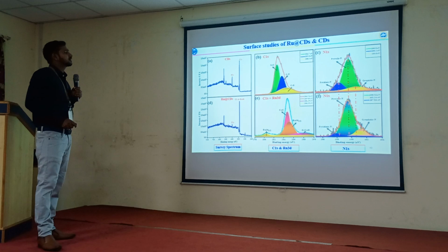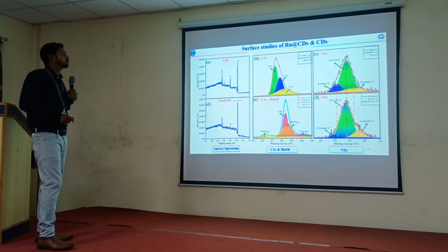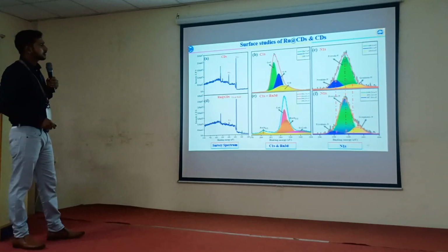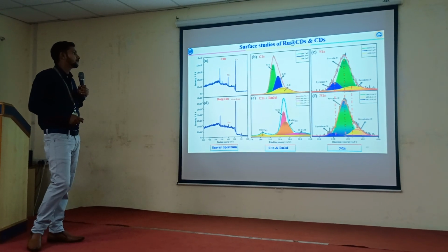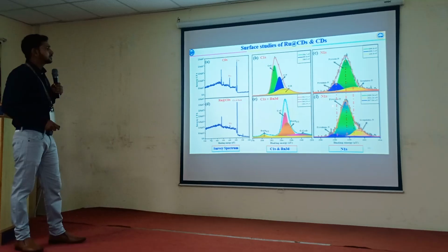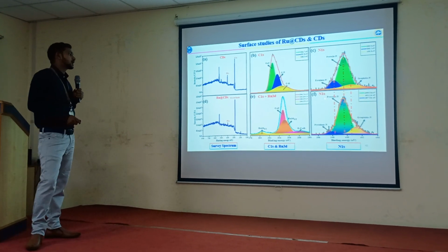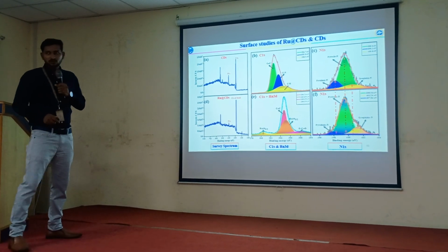And figures C and F represent the N1s spectra of carbon dots and ruthenium carrying carbon dots. Here the ruthenium carrying carbon dots N1s spectrum experiences a shift in binding energy when compared to the carbon dot spectrum in the pyrrolic, pyridinic and graphitic nitrogen, which further confirms that these are the active moieties involved in the stabilization of ruthenium 2+ in the carbon dots matrix.